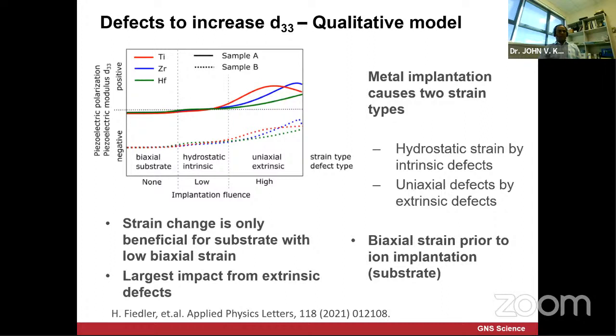So what it gives is that metal implantation causes two strain types. One is a hydrostatic strain by intrinsic defects, and the uniaxial strain by extrinsic defects. So the strain change is only beneficial for substrates with low biaxial strain, because it doesn't change any of the other properties. It actually helps to propagate the waves, because it's all about acoustic waves, in a better way.